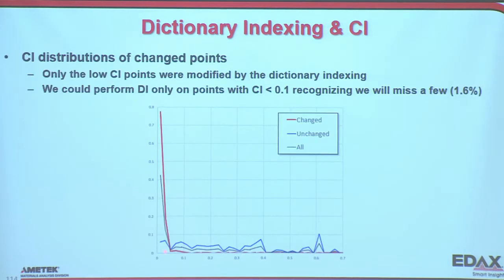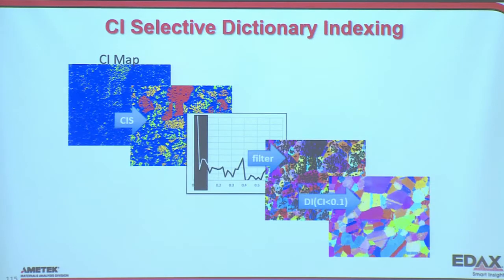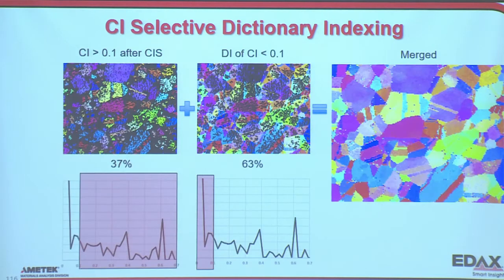And what I find is the low CI data is the data that's changed. So the data between the Hough and the dictionary indexing, the values that have changed, the orientations that are changed, are all caught by the low CI values. So what that means is I could filter my data so that I only do dictionary indexing on the low CI points. And so here it is. Here's the data. So here's the filtering.